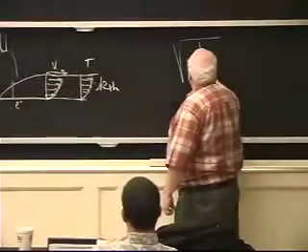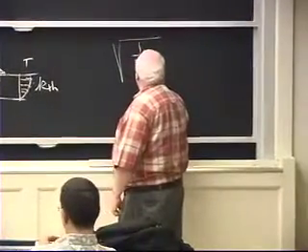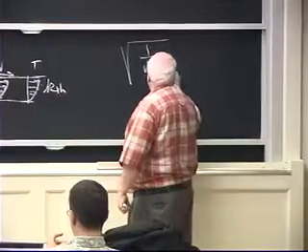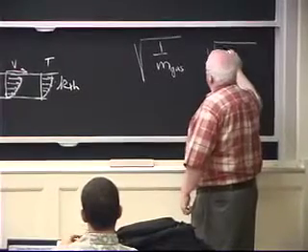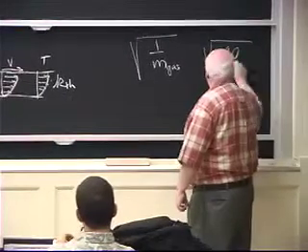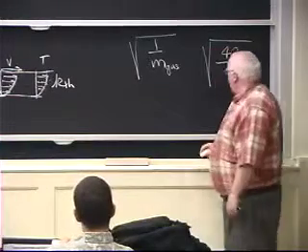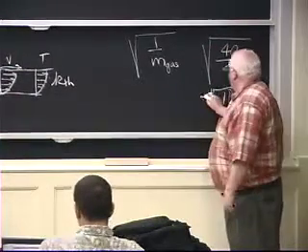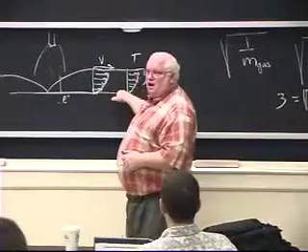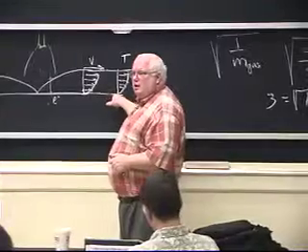Okay? But if 80% of heat is going to come from the electrons, helium has a much higher thermal conductivity, and in fact, the thermal conductivity of the gas goes as the inverse square root of the atomic mass of the gas, if you go through the kinetic theory of gases. So if I wanted to compare argon to helium, argon has an atomic weight of 40, helium has an atomic weight of 4. The square root of 10 is equal to 3. You know that, you're in the math department now, right? And so there's about 3 times the thermal conductivity of helium across this gas boundary layer as there is of argon.